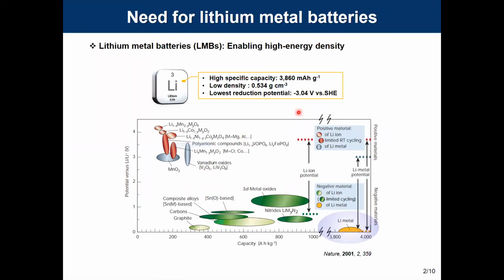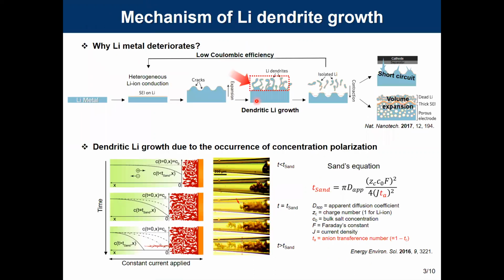Why do we use lithium metal batteries? Lithium is the most promising anode for obtaining high energy density due to its high specific capacity and low reduction potential. However, it has an issue of low Coulombic efficiency and volumetric expansion due to lithium dendrite growth, which are a serious challenge that contributes to safety issues and cyclability.